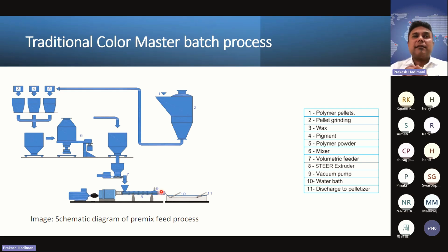Okay. Since currently the industry is using the traditional method, what is the traditional method? You are putting polymer, waxes, and other ingredients, and you premix 100% in a high-speed mixer, and you dump it into the volumetric feeder or a gravimetric feeder. From there, you are discharging through the hopper, and then the dispersion and distribution take place inside the extruder, and devolatilizing, and these strands are quenched in water, and then the strand surface water is removed with an air knife, and then pelletizing is done. This is the current standard traditional method everybody is following.